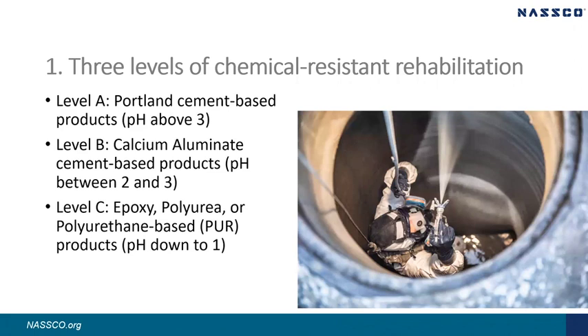First point that I would like to make is that it is useful to break down the types of solutions into 3 levels of chemical resistance. Level A products are Portland-based cement products. They provide an excellent seal and can provide structural benefits, but they only perform well in non-acidic environments with a pH above 3. Please understand that the pH scale ranges from 0 to 14. A pH of 7 is neutral, while lower pHs become more acidic and higher pHs become more basic. Our skin has a pH around 5.5, so we are actually a little acidic. Portland-based cements will disintegrate when exposed to pH environments of 3 or less.